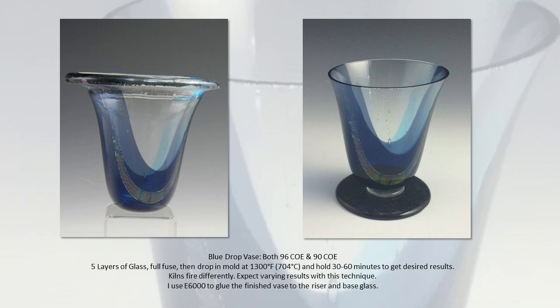I included some of the information on how I fired this. It was 5 layers of glass. I full fused those layers. Then I placed the fused glass on a drop mold and I fired it to 1300 degrees and held it there anywhere from 30 to 60 minutes to get the desired results. Kilns fire differently. Expect to have varying results with your kiln and your materials. I use E6000 adhesive to glue the vase to the riser and that little base piece of glass that I made after the vase was completed.